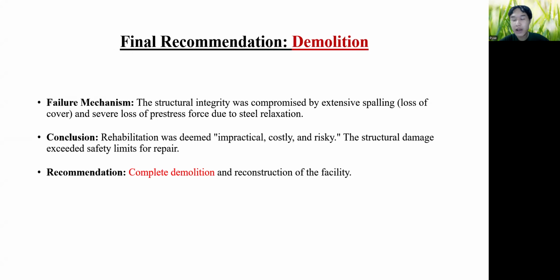So, the final recommendations. In this research paper, there were a lot of tests: non-destructive, destructive, core assembly, and simulation. After that, the author gave out a final recommendation, which is demolition, because the failure mechanism is that the structural integrity was compromised by extensive spalling. Loss of cover happens, and then internal strands are exposed to air, which could lead to total failure later. And severe loss of prestress forces due to steel relaxation happens as well.